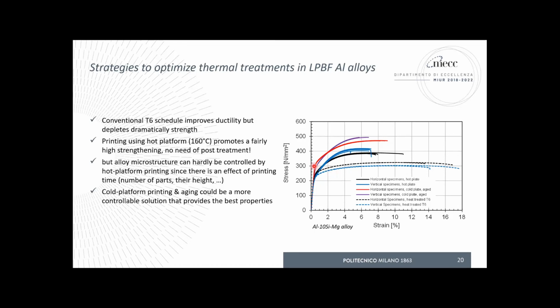Okay, we have quite low strength but high ductility. However, the bunch of curves here in the middle, the blue and the black one, correspond to the samples that had been printed with the hot stage, with the hot platform. So they are already aged in the machine. They show an increase in the strength over the standard T6 treated alloy. And that's not bad. It's a good idea, because in principle you can save the post manufacturing heat treatment.